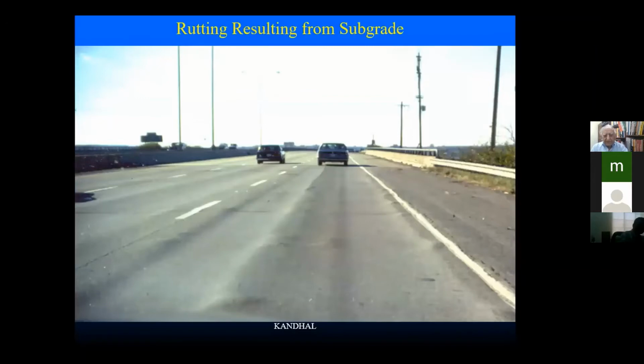Now here we are talking about rutting. We said rutting can happen due to a subgrade which is not strong. Rutting can also happen because the bituminous layer doesn't have enough strength. Now in this case, although I have to verify it, if I go on this job and I see this kind of rutting, I would say that it's happening because of a subgrade which is very weak.